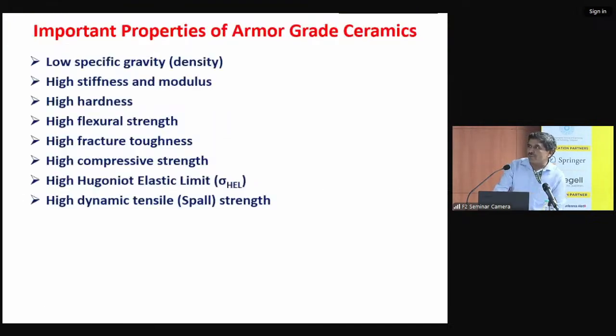And these are some properties of the foam. Basically, we just see what the important properties are for the armor grade ceramic to be used as a front facing. The density should be less. It should have high stiffness and modulus. Hardness is extremely important, because as I told in the starting, now we are having hard steel core bullets. So the front facing has to be hard. So hardness of the ceramic plays a very important role, and the ceramic should also have high fracture strength.